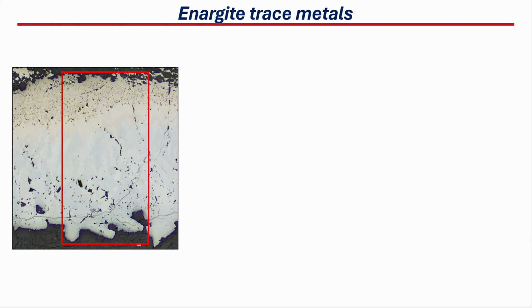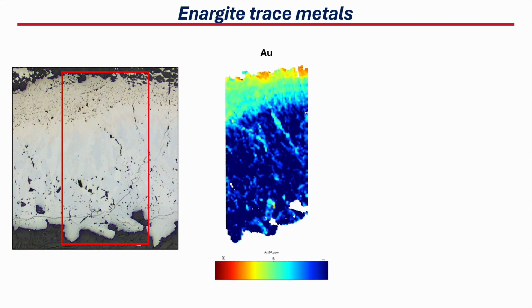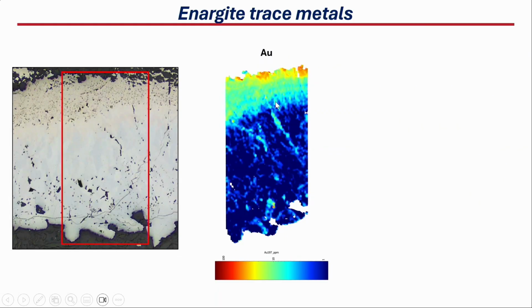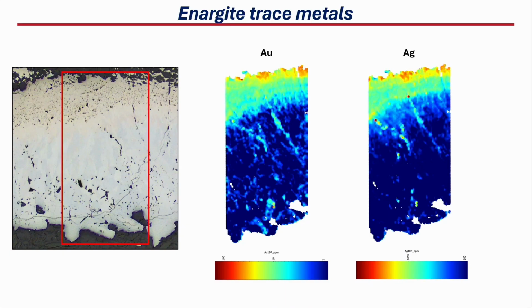So just to show you a little bit of the trace metal distribution in enargite, this is not the exact same area I showed in the previous slide, but we did some laser ablation mapping, and what we saw is that actually most of the porous enargite is the one that contains the metals, up to 10 ppm of gold. Although there are some regions on top that can even reach 100 ppm of gold. Silver follows the same pattern as gold, where in the porous area we can find the highest silver grades.